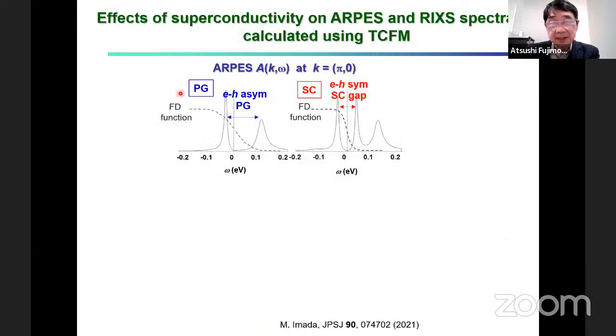And this is a calculation of the two-component Fermion model for the ARPES at pi zero, in the pseudo gap state and the superconducting state. In the superconducting state, the gap is symmetric, but in the pseudo gap state, the superconducting gap disappears, and the gap can be asymmetric. The empty part of this gap can be detected by ARPES, because at high temperature above TC, the Fermi-Dirac distribution function remains finite above the Fermi level.